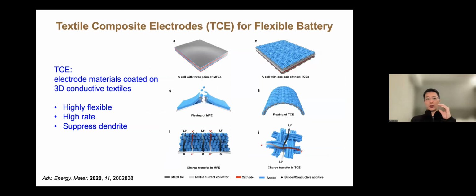porous conductive fabric. Since the fabric always has some porous structure, roughly about 67%, the electrode slurry will penetrate into the pores and form a 3-dimensional interpenetrating composite-like material, right? That's why we call it a textile composite electrode. And what we found is that this kind of composite electrode is, naturally, extremely flexible. It can go through tens or hundreds of thousands of bending cycles without an obvious decrease in properties.